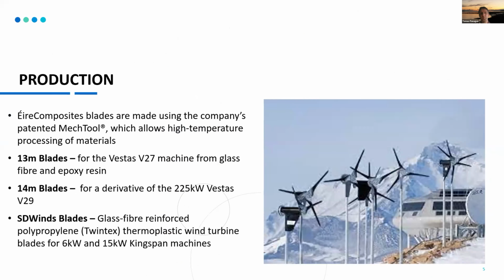The production blades, these are the small black blades you see on the right. And the picture is actually in Antarctica. So these are made using heated metal molds and processed around 200 degrees. And the Twintex material, the polypropylene, it's good for this kind of smaller blades, but it doesn't really work for the higher loads on the bigger blades.